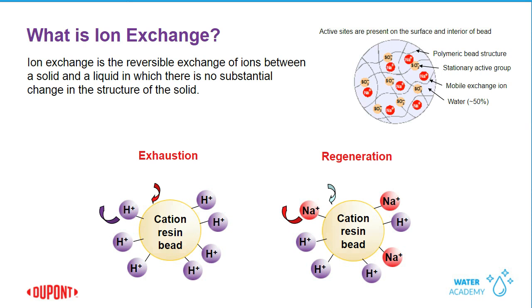And as the resin will continue to do this, and as it exhausts, we stop and we regenerate this resin with acid, which allows us to put the hydrogen back on the resin so that it is ready for the next service cycle to remove even more contaminants.